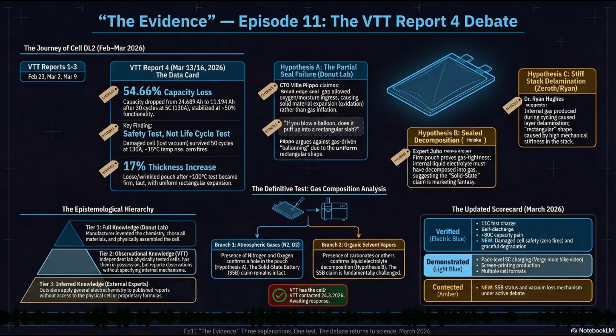Yes, but by the end of the test, the physical thickness of the cell had increased by 17%. 17% thicker. And the pouch was no longer loose. It was completely firm and taut. It swelled up. But what about the temperature? I mean, if you push 130 amps through a degraded, swelling battery, the resistance must be skyrocketing, right?